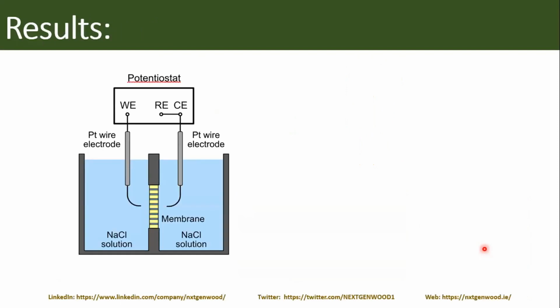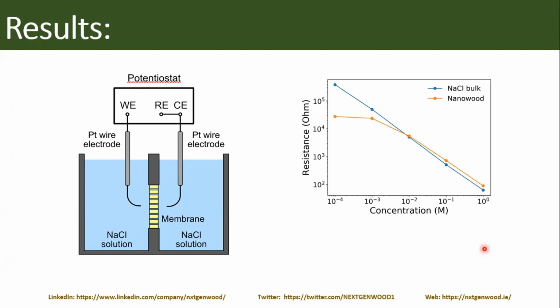And first, before I switch to thermoelectric properties, a few words about characterization of these membranes. So we need to make sure that we have nanoconfinement, and for that we use just electrochemistry, electrochemical impedance spectroscopy, because we can measure resistance of these membranes. And if we do it, we receive such a curve. So here we have a resistance of our electrolyte in a membrane, measured between two platinum electrodes placed very close to the membrane. And as you can see, this is a resistance as a function of concentration in log-log scale.